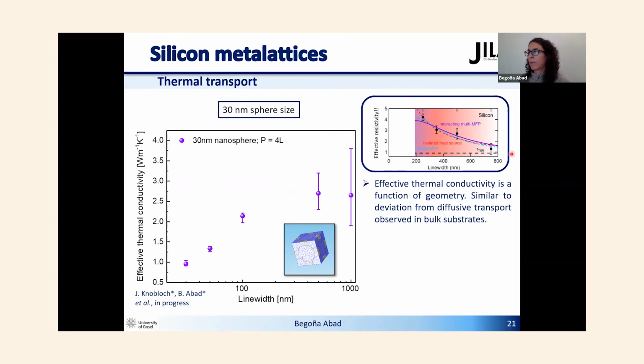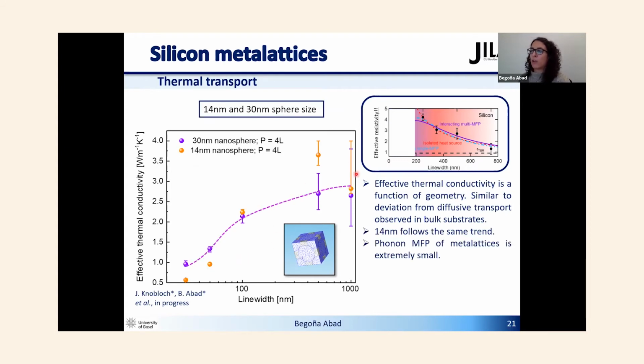And if we compare with the plot that I showed earlier, we find a really strong similarity between the two, because in that case, this was effective resistivity, and this is effective thermal conductivity. So one is the inverse of the other. So at the end, they are very similar. So something similar to what was happening in the silicon is also happening in this type of metalattice. Also, if we look at the 14 nanometers diameter metalattice, we see the same kind of behavior.